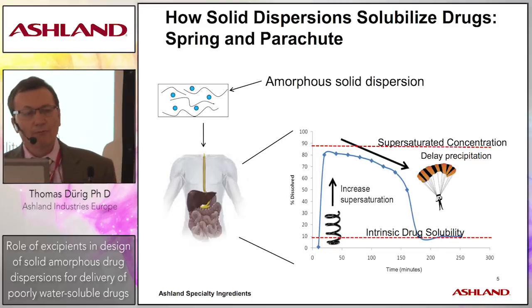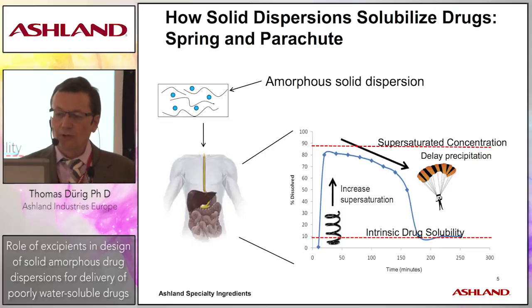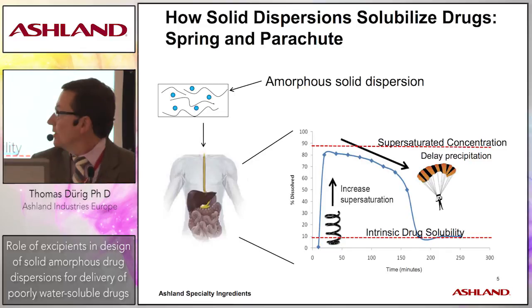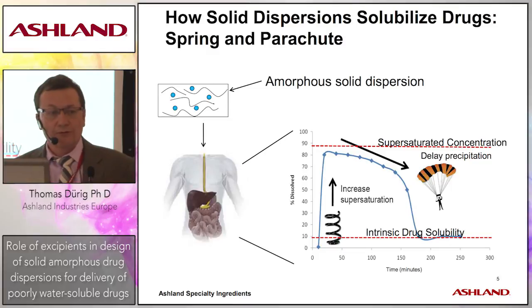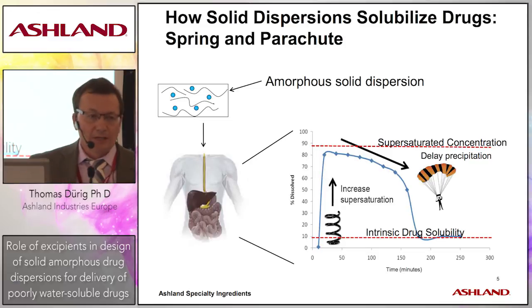And the problem with supersaturated solutions is that they also are unstable, and the drug would naturally tend to want to form little crystals at this high level in terms of concentration, and start precipitating. So the risk is always, if you do induce this highly supersaturated state, much higher solubility, that you might get very rapid recrystallization, sort of like a sharp little peak, so that you really didn't get much benefit.